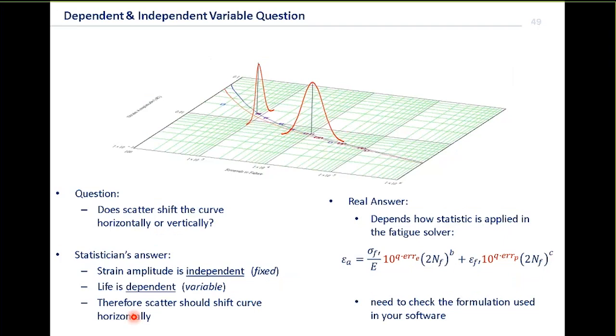The reason that this is complicated is that the statistician will answer one way, but it really depends on how the equation's written. So the statistician's answer, and them being quite right, is that the strain amplitude in this case is the independent variable. In other words, that's the one we know is true. We set our rig up with the strain amplitude fixed. It's constant. That cannot vary statistically. So in theory, there's no way the curve should move up and down. The dependent variable is life. That's the thing that changes statistically. So the curve, in theory, should move left to right, dependent on the reliability that we're after.